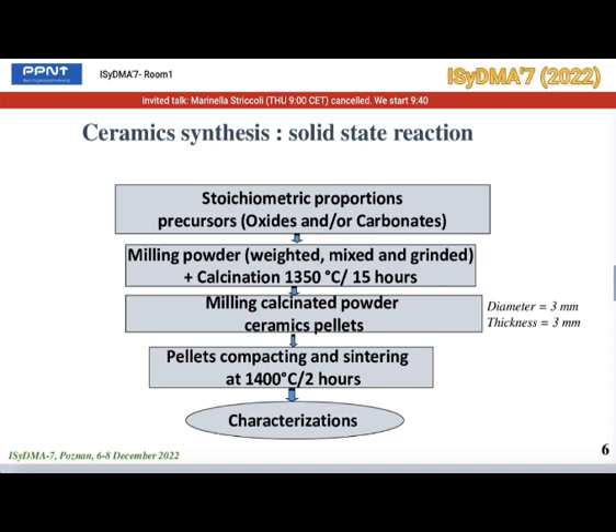Concerning the ceramic synthesis, ceramic pellets with a diameter of 3 millimeters and a thickness of 3 millimeters were prepared by solid-state reaction method. Samples were prepared using stoichiometric proportions of carbonates and oxides. Appropriate quantities were weighed, thoroughly mixed and pestled, and subsequently calcined at 1350 degrees Celsius for 15 hours. The obtained powder was ground and then pressed into pellets. The pellets were subsequently sintered at 1400 degrees Celsius.